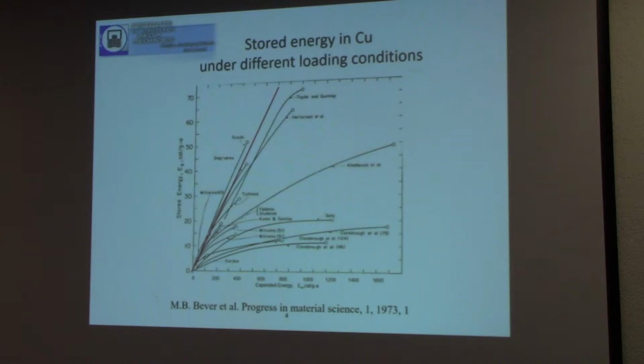so-called less than 10%. Generally, the people who work in the theory of plastic deformation say that stored energy is several percent of plastic work, and it's not interesting to take into account. Here, all experimental work is with copper with completely different loading conditions, and we can see that a lot of results are less than 10%. But 10% is pretty big.